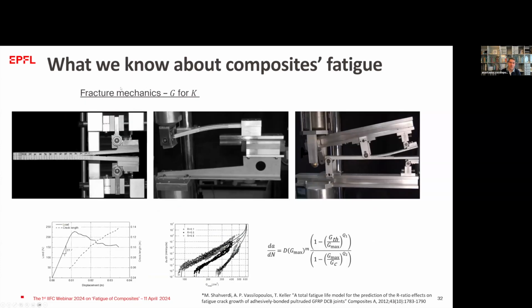So I discussed before also about fracture mechanics. And of course, in composites, we have a lot of fracture mechanics used. There is a big discussion about using the G, the strain energy release rate, instead of the K, the stress intensity factor, especially because for composites, it's very difficult, if not impossible, to calculate successfully K values when we have cracks with large process zones and so on. But anyway, we did tests. We are doing a lot of tests, mode 1, mode 2, mixed mode testing for composite laminates, for composite joints, as in this case that I'm showing.